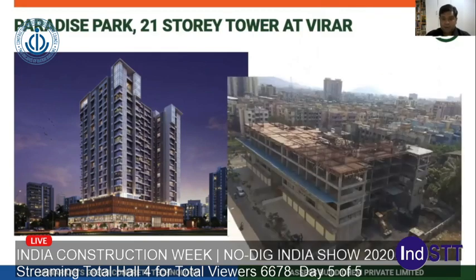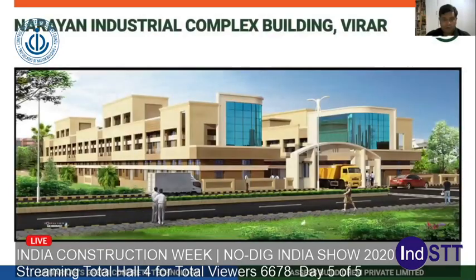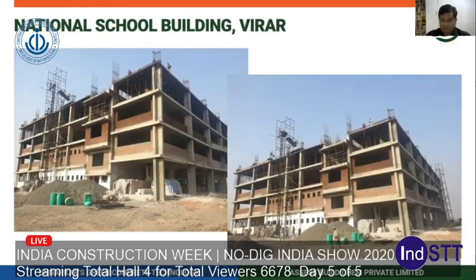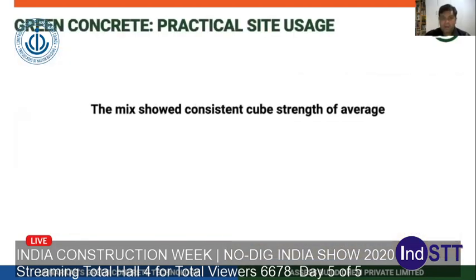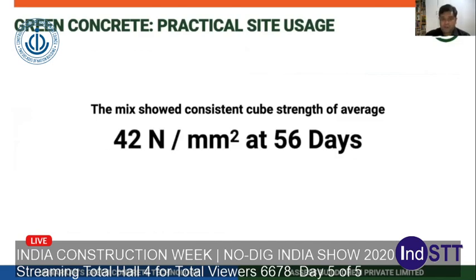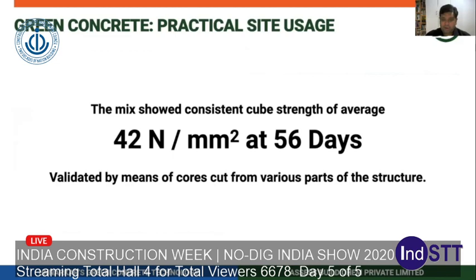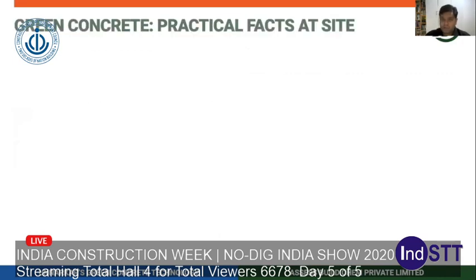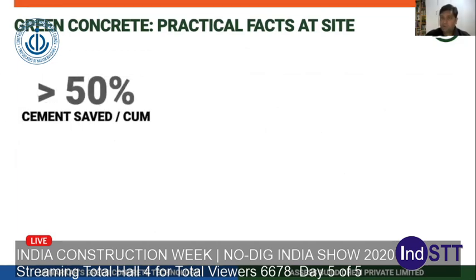It has been used at multiple sites in and across the northern Mumbai region. We've used it for an industrial complex, a high 21-story tower building, and we're using it for a school building. You can pretty much see how the finishing and everything looks. It's done beautifully. The quality is controlled. At site, in terms of quality, we did a lot of pouring and a cross verification, and the concrete was consistently showing cube strengths of almost 42 Newton per mm squared. We also took cores, tested the cores, and they correlated to the cube strength. So overall, the performance was pretty consistent, and the durability pretty good.